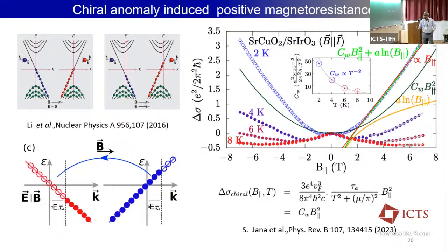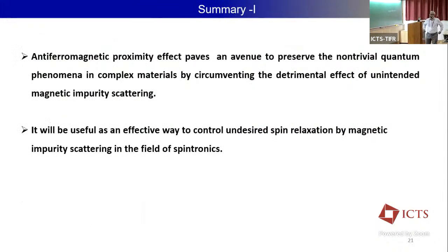If anybody is interested, they can go through it. This was last year. So, in summary, what I wanted to tell you is that the antiferromagnetic proximity effect paves an avenue to preserve the non-trivial quantum phenomena in complex materials by circumventing the detrimental effect of unintended magnetic impurity scattering. Because in any material there could be some ppm level magnetic impurity, and that could affect your quantum transport very much. And this method, by just sandwiching an antiferromagnet, will possibly be an effective way to control undesired spin relaxation by magnetic impurity scattering in the field of spintronics.